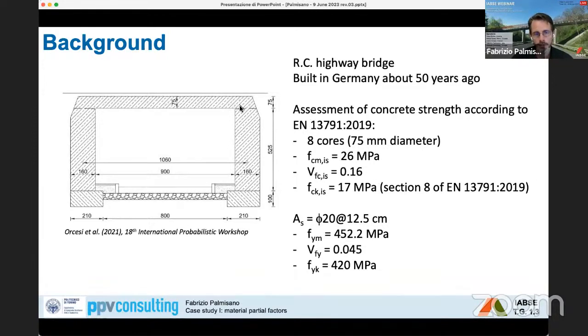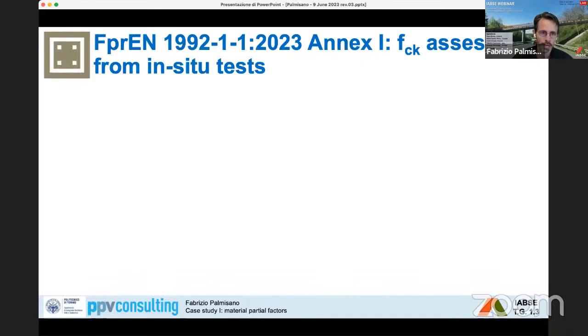The reinforcement of the slab is composed of 20 millimeter diameter bars with a spacing of about 12 centimeters. The yield strength has been assessed by taking samples and testing them in the laboratory, and the characteristic value has been obtained by using a log normal distribution.